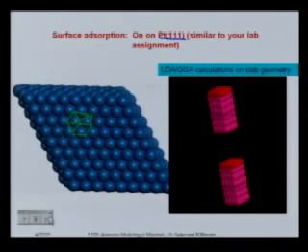So if you want to study the adsorption of something like hydrogen or oxygen, again, you build a lattice model. Then you have to do density functional theory calculations to parameterize it, and I think you've done that now in the lab. Because this is a surface, you would set up a slab geometry. You would take a few layers of platinum and put stuff on the surface to adsorb it. And you put a range of vacuum above that and do the DFT calculations.